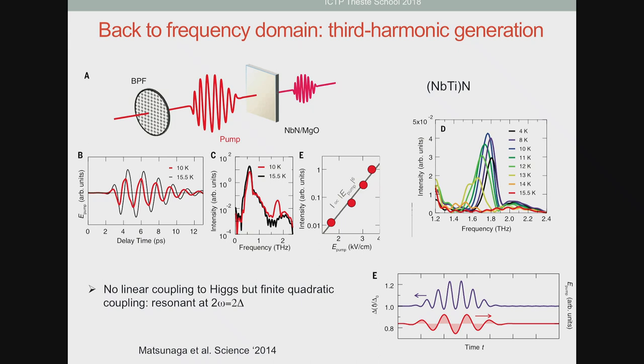So this is actually interesting. You can do a much simpler measurement, and these guys did this simpler measurement. You can say, okay, there is an E square signal, so I'm shining E, and I collect some E square signal. Actually there is another third order nonlinearity that is much simpler: third harmonic generation. I shine omega, and I look at a signal at 3 omega. This is also a third order nonlinear susceptibility. So you can do not a pump probe measurement, but really just a very simple nonlinear optics measurement. You shine a terahertz light, and you look at its frequency domain composition upon passing through the sample.